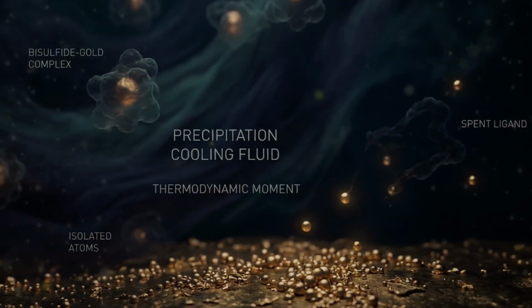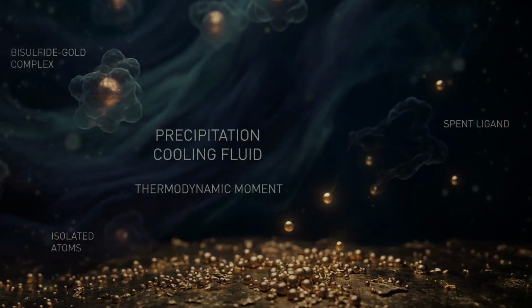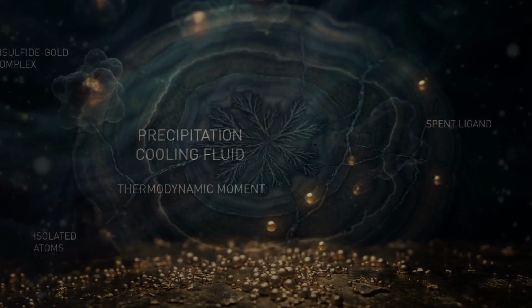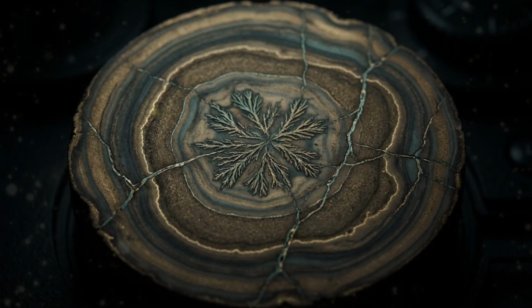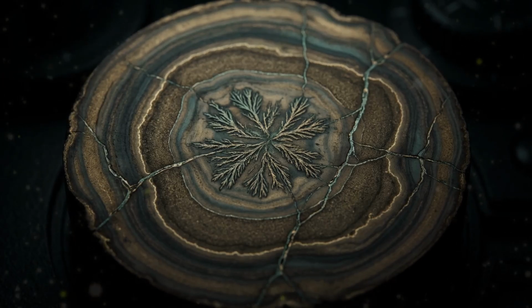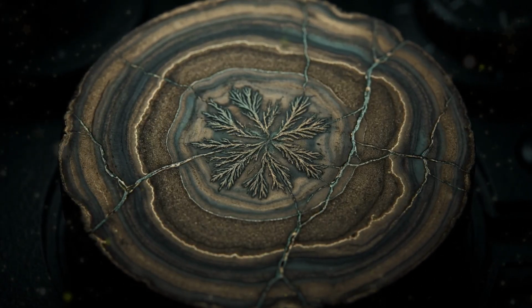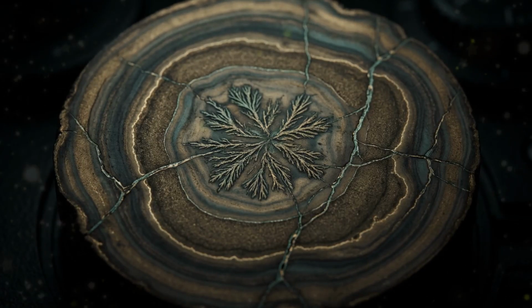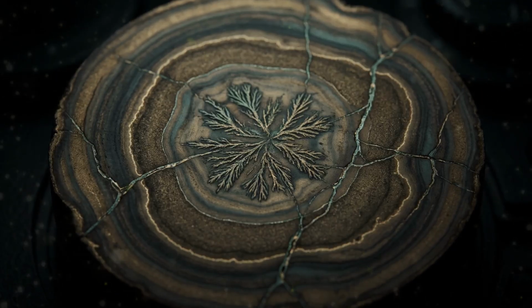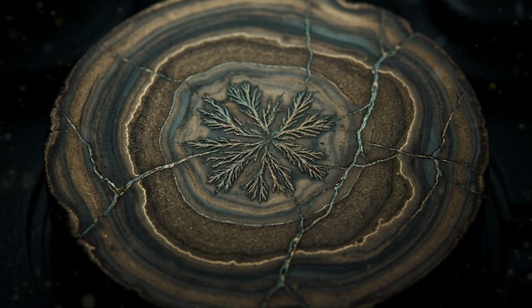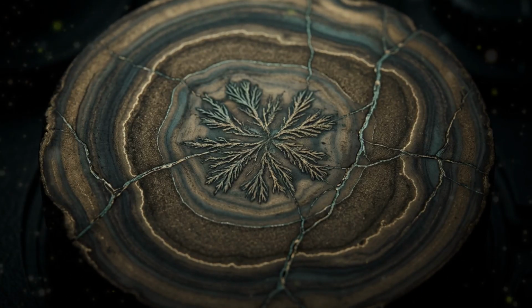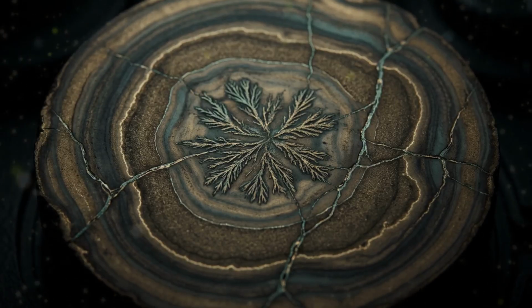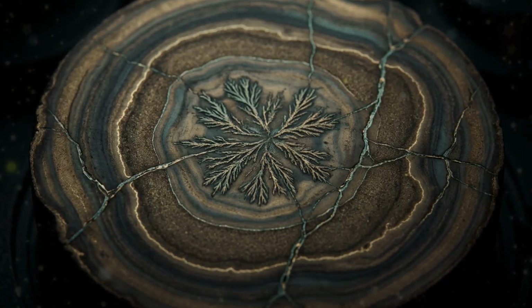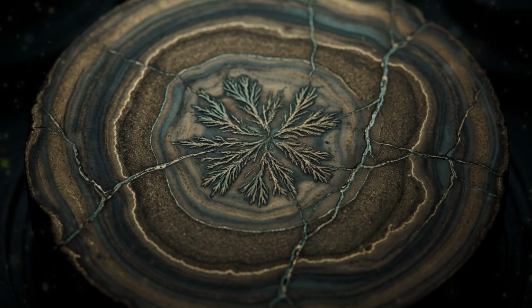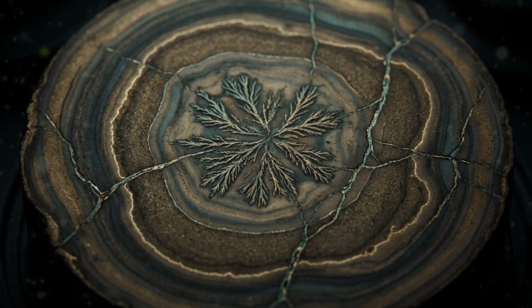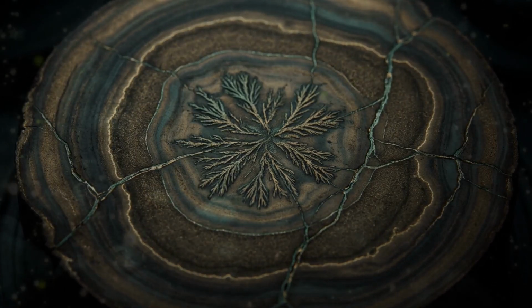Gold nuggets found in hydrothermal vein systems are not simply chunks of crystallized gold from solution. Their internal structure, revealed by careful polishing and microscopy, tells a complex history. Primary crystalline gold with dendritic or fibrous texture from the initial deposition, overlaid by subsequent layers of coarser crystalline gold, the whole cross-cut by fractures, later healed with additional gold deposition. This layered structure records multiple episodes of fluid flow and gold precipitation across the history of the hydrothermal system.